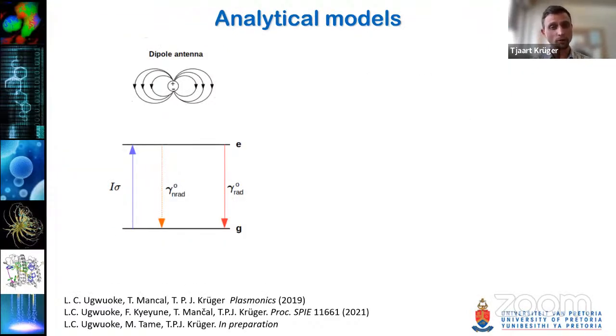Okay, we also proceeded to model this, and I'm not going to go into a lot of detail, just a single slide on that. So our LHC2, even though it contains 54 pigments, it can still be modeled as a dipole point source. And that is because 90% of the emission comes from the lowest exciton state. And this lowest exciton state can be considered to be an emitting dipole. So we consider our whole complex to be a single point dipole antenna. And the rates of relevance are the absorption rate, the non-radiative decay rate, and the radiative decay rate.